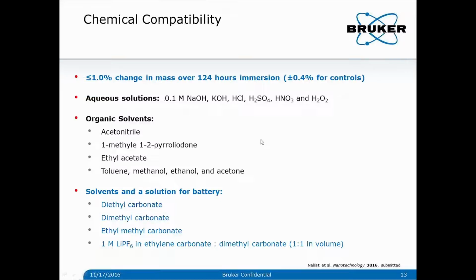For this nanoelectrode probe, the components for assembling it, including the glass and the epoxy, we have tested extensively for chemical compatibility in a wide range of liquids. Over 124-hour immersion into the liquids listed here, it shows less than 1% change in mass before and after the immersion. These liquids include aqueous bases and acids, and some of these acids, for example nitric acid and hydrogen peroxide, are strong oxidants.